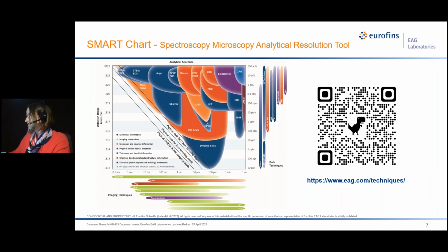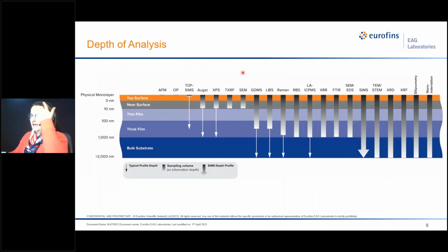So this is a very good chart to compare your technique of interest to XRD and see how that lines up. The other thing we can look at is the depth of analysis. And so, for example, TOF SIMS has a very shallow depth, but XPS and Auger have more depth that you can penetrate into the sample. But the arrows indicate that deeper depths are available by depth profiling, but not necessarily a standard technique. So again, over here, you can see the XRD, we can probe, you know, top surface down to bulk substrate material.